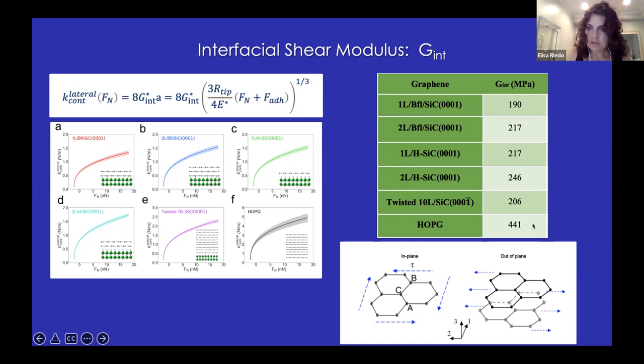And these are the results. So for the different samples, we obtain values of the order of 100 megapascal. So the first observation is that the modulus that we are measuring is indeed not the shear modulus of in-plane graphene, because if we would stretch the graphene layers, we would get values that are more of the order of the terapascal. On the other hand, we measure very low values. So these very low values indicate that what we are measuring is more the out-of-plane shear modulus, which is what I anticipated at the beginning. So it's really the sliding of the top layer compared to the substrate.